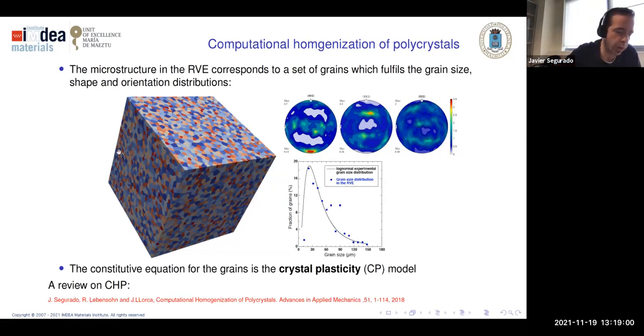Okay, this is the microstructure, the RVE. The second thing is the constitutive equation. If we're doing polycrystalline homogenization, the constitutive equation is the one that applies to a grain. And this grain behaves as an elastoviscoplastic material, and it's absolutely anisotropic depending on the lattice and the orientation. And this is well represented by the crystal plasticity model.